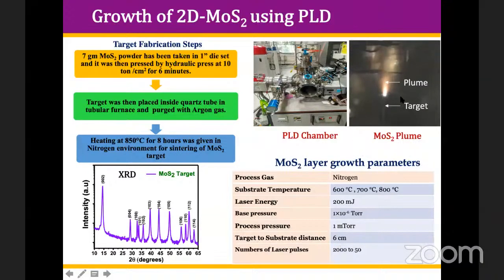And since we need a ceramic target here to interact with the laser to create the plume, we have to mix the powder, press it by hydraulic press, and sinter it to make a solid target. And the target, you can see here, is placed in the inert atmosphere, and then the sintering